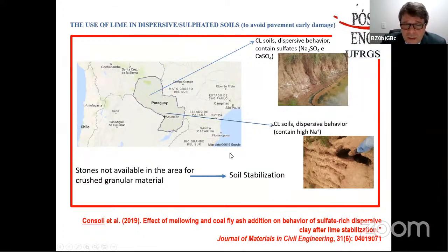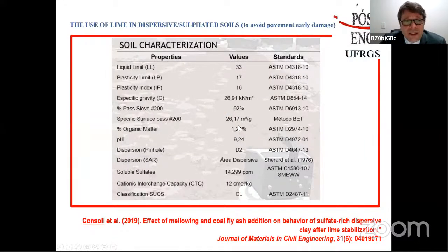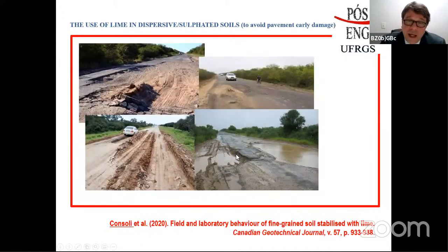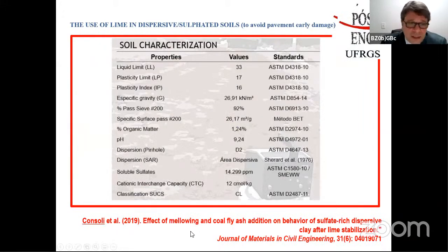And one of the ideas of using this material is to stabilize with lime, with cement, or even with some other kind of cements that you might use. And just to have an idea regarding one of these sulfated materials, the amount of soluble sulfates is about 15,000 parts per million, which is quite above the usual ones. And for usual cases, it's not possible to treat it with any kind of cement. However, we went on, and in this paper we used the mellowing technique, and we also added some coal fly ash as a precursor together with lime, and we have been able to solve the problem.